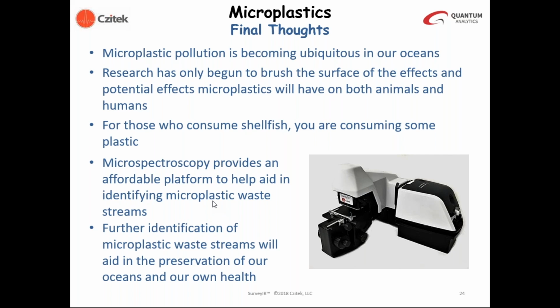And then another factor is the detector itself. In the low-cost compact FTIR spectrometers, typically that is a deuterated triglycine sulfate detector. In some other spectrometers, one can mount what's called a mercury cadmium telluride detector, which is a much more sensitive detector than TGS, but it requires liquid nitrogen cooling. With that kind of detector, you can analyze specimens which are 10 micrometers or greater because of the sensitivity of the detector itself. But most commonly with SurveyIR, a deuterated triglycine sulfate detector is used.